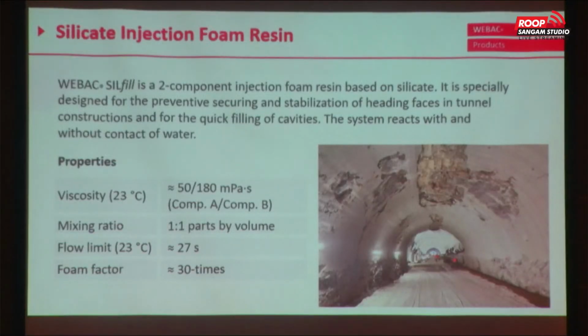Reaction time is really fast. We speak about 30 seconds, then the foam starts. But keep an eye on the viscosity. It's 50 mPa·s. It's like water. But after 30 seconds, you get a high expansion of that, and you get a high foaming capacity and the lightweight foaming with a 30 times or 40 times foaming factor.